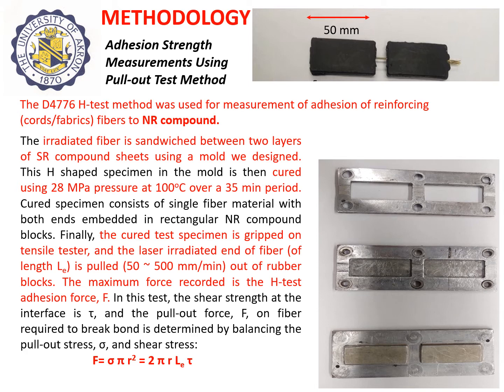The pull-out test we used was similar to the ASTM D4776 test, but we designed and manufactured our own mold in-house, which is shown on the lower right. The cavities are used to lay down the layers of the partially vulcanized rubber sheets, in between which the nylon cords are sandwiched. The embedded length is induced on one of the sections of the mold, one of the cavities, and the other side contains a full length of the fiber, which when closed and cured produces the sample shown on the upper right. And then this sample is gripped in a tensile test machine and pulled to obtain the pull-out force and shear strength.